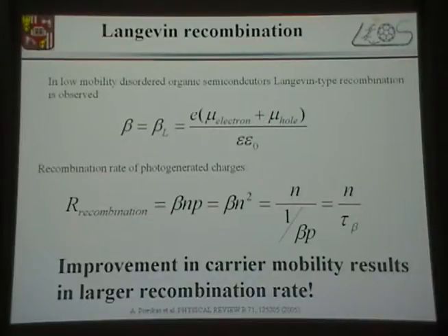But so one can ask the question, if we want to reduce the recombination rate for organic solar cells, we would probably like to improve the charge carrier mobility. But you see that if the mobility is improving, the bimolecular recombination coefficient is also increasing. Therefore, the recombination rate will also increase. So these processes might go hand in hand, and the gain in mobility might not necessarily be a gain in efficiency or in the photocurrent.